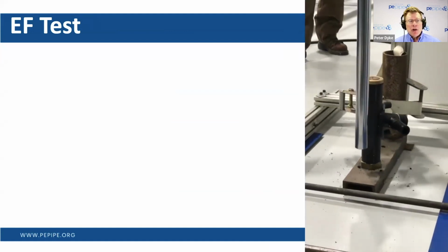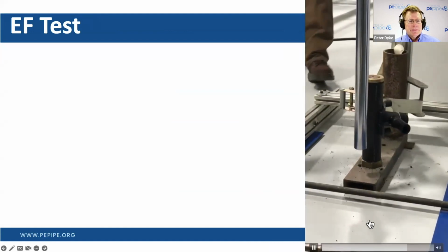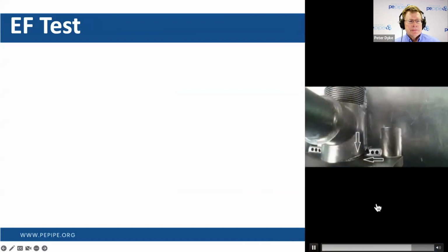All right, so this one broke at the stem. Let's look at that a little bit more closely. So right here is the stem, the smokestack. Here's the saddle, and it ripped off here. Had we not peeled and cleaned properly, that saddle would have popped off under all that stress.